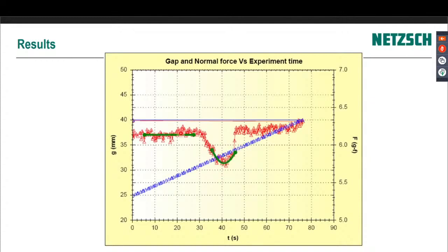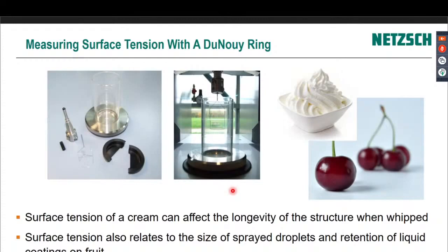second order polynomial, and we find the average of the first 15 seconds of that graph. And from the difference between the normal force at the beginning and during lifting the meniscus, you can see how much of the liquid was lifted up by surface tension. And then you use a calculation as calculated by Du Noüy, and that will show you what the surface tension is.